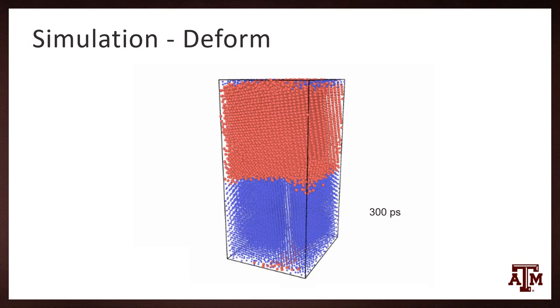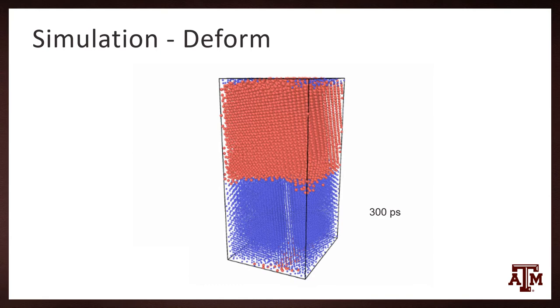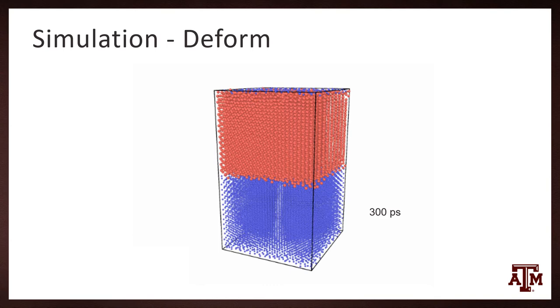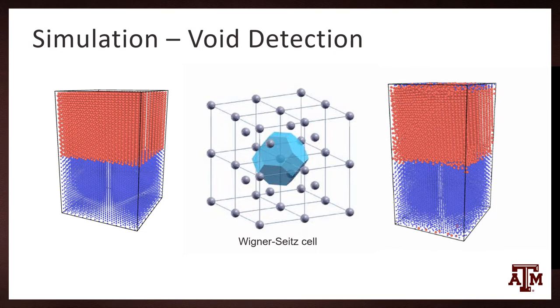The stretching along z is evident, though much harder to see. Some twins form along the microstructure momentarily, then move up and out of the simulation box. Within the box, the atoms respond to tensile stresses by separating somewhat, making vacancies and eventually voids in the material. The stress at first void nucleation is well correlated with spall strength, so I measure the time and stress at which the first void nucleates.